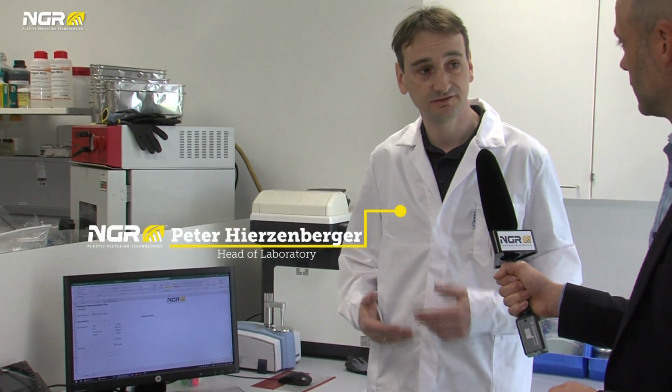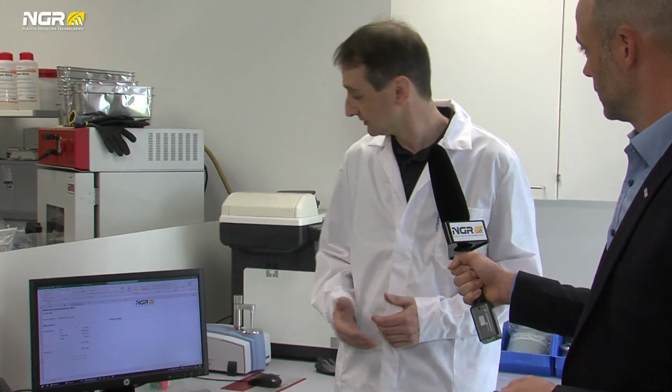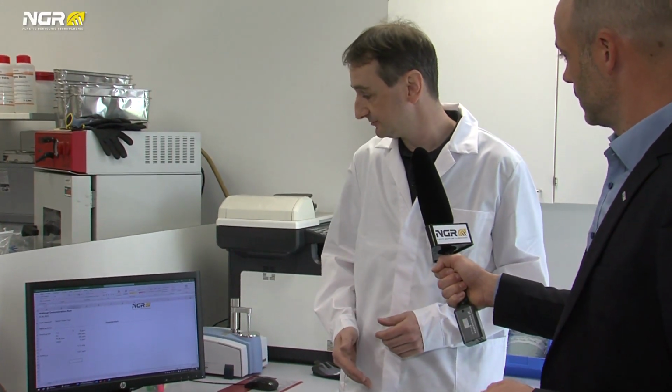Yeah, David, as you mentioned, we did a roasting test at 220 degrees for 1 hour in order to find out contaminants, especially PVC, polyolefins. We measured the moisture and the intrinsic viscosity. Those are the results we found.